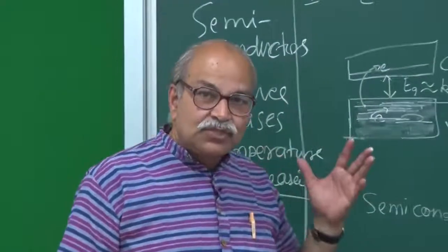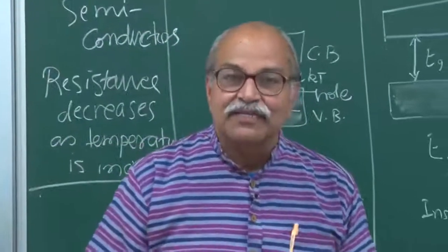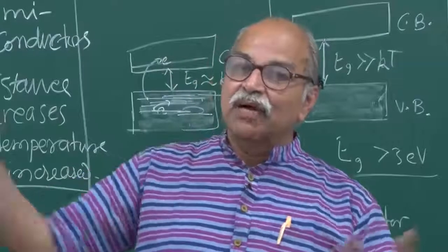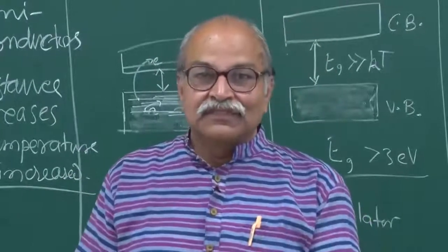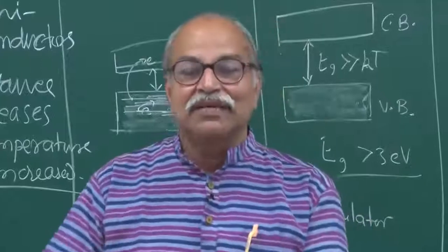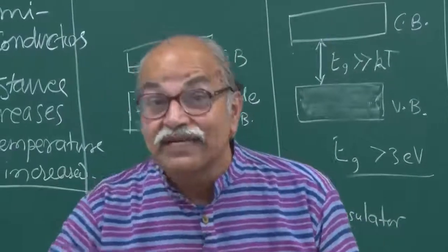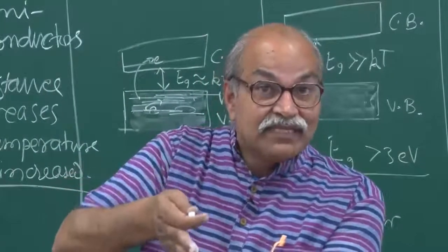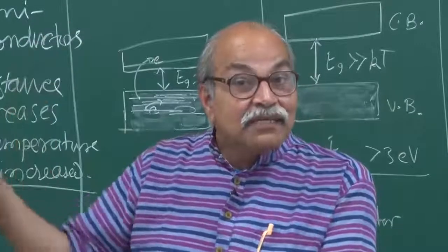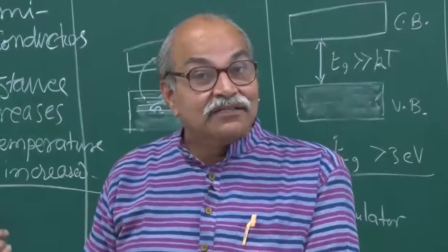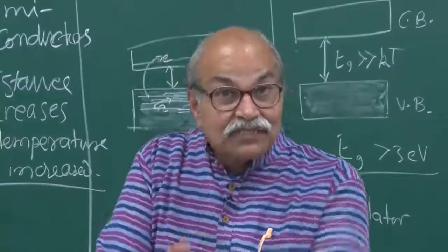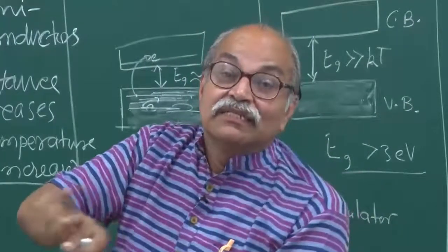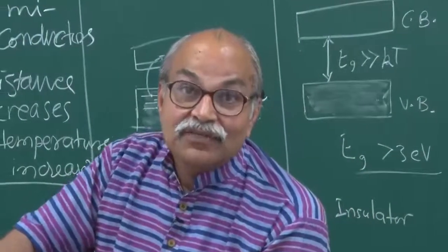This can be used to identify experimentally which material is a conductor and which material is a semiconductor, or if in some process there is a transition from metal to semiconductor or metal to insulator, going towards insulator. If there is some kind of transition, that transition can be identified experimentally by looking at the temperature dependence of the resistivity, and you can identify when it was in that conducting zone, and when it becomes in this semiconducting or insulating zone.